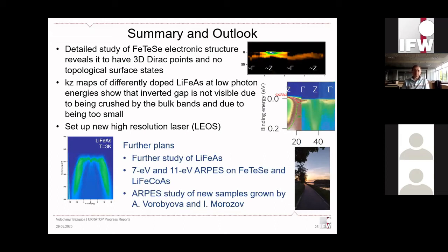For LiFeAs, we managed to get low photon energies map, and the inverted gap is not visible on it due to the gap being too small and due to the too high intensity, too strong bulk bands. Also, a new laser was set up. A lot of other things were done in the process, like the SUMA test and others, but let's not focus on this for now. And my further plans are the continuation of the study of lithium iron arsenic with other types of doping, with higher doping of cobalt maybe,